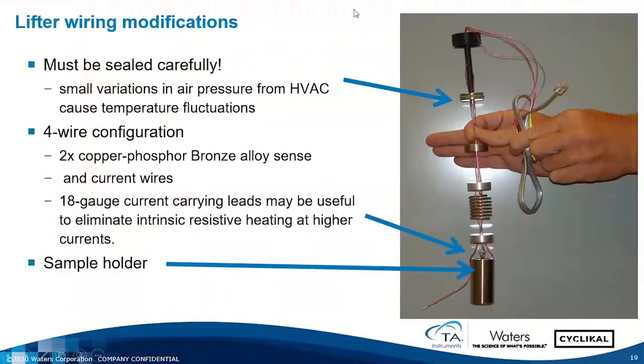Lifter wire modifications. Over here, I'm showing our lifter, and I understand that TA now is providing a wired lifter for such calorimeters, but when we started this work, that wasn't possible. So what we had to do is modify our equipment, and we did that by drilling holes in the thermal shunts. There's a thermal shunt here, here, and here, wires to the top. This is the most important thermal shunt. We drilled holes in that and then extended our wires down into the sample area.